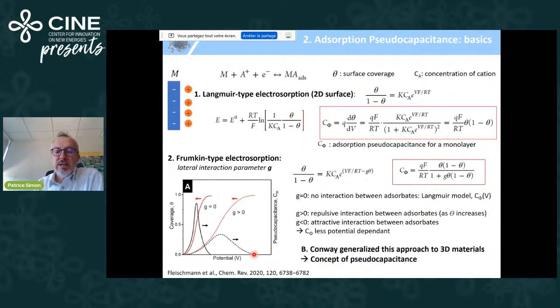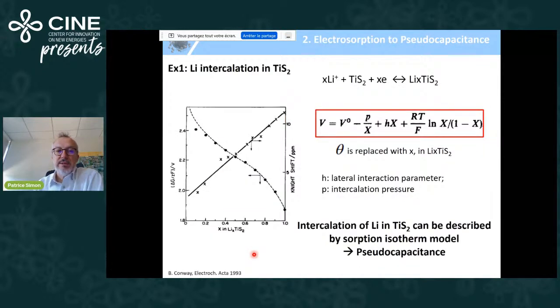And Conway generalized this approach to 3D materials, and he proposed the concept of intercalation pseudocapacitance. This is the first example: lithium-plus intercalation in TiS2. This is the equation in non-aqueous electrolyte, and this is the change of potential versus the number of lithium in TiS2. You end up with this kind of equation to depict this intercalation, where you replace theta, from the previous equation that we saw, with x, x being the number of lithium in TiS2.